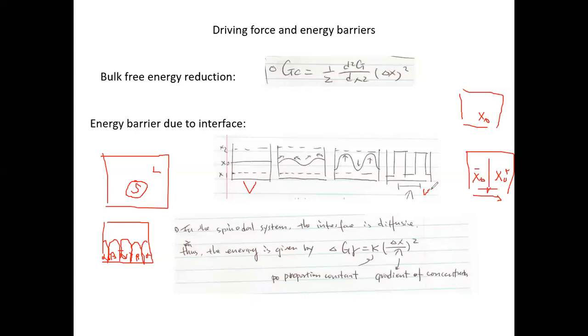So the interface in this system basically depends on, if you go from one direction to the other direction, how sharp a difference the atom feels. In all these cases, if you travel from one direction to the other, the atoms feel a very sharp change from one phase to another. But in the spinodal decomposition, the phases are gradually developing. So the atoms initially do not feel a very sharp change in their environment. So they do not feel an interface, and this interface is gradually developed during the transformation. Do we see that? This is what we call a diffusive interface, in contrast to the sharp interface in these two cases.